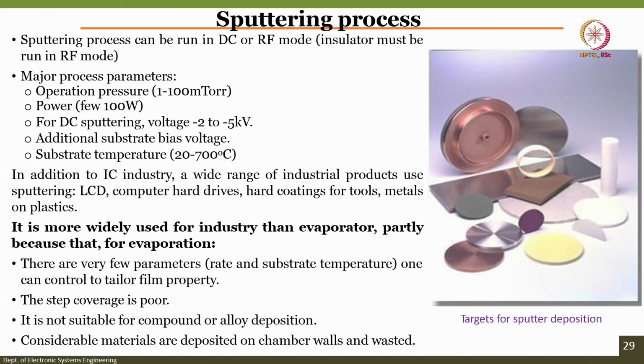For DC sputtering, the voltage is between minus 2 to minus 5 kilovolts. Additionally, we can apply a substrate bias voltage. Substrate temperature is about 20 to 70 degrees centigrade. That's why sometimes you have to cool the substrate. In addition to the IC industry, a wide range of industrial products use sputtering.